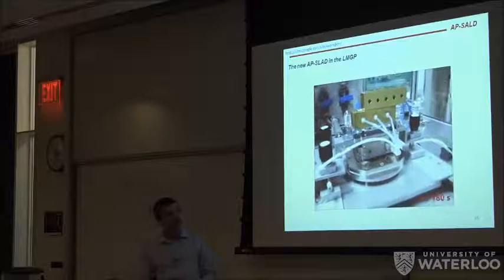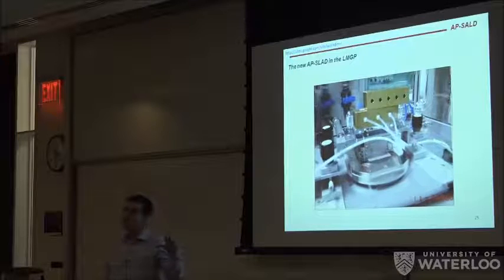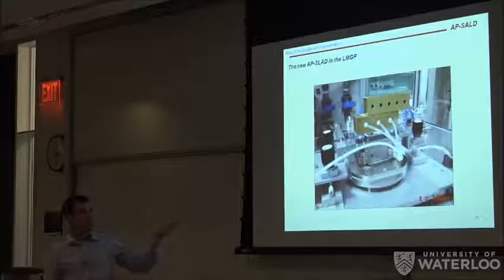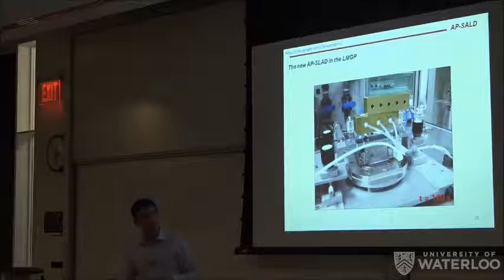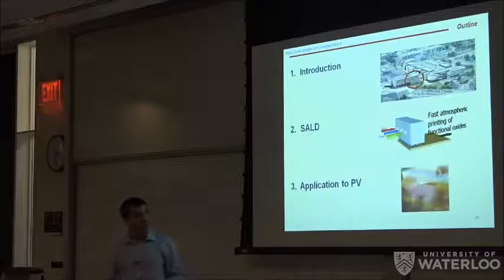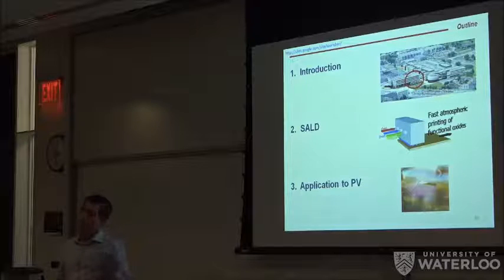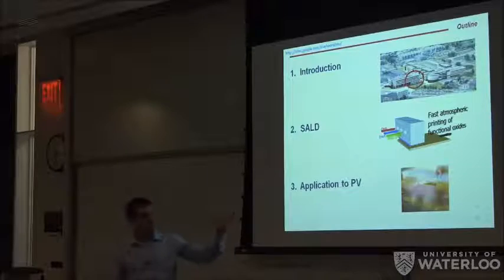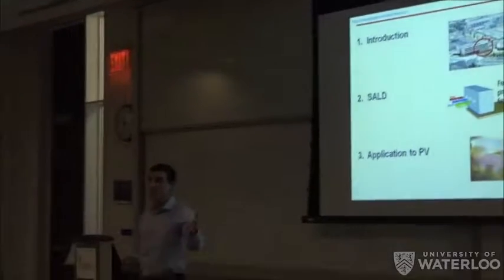So it's really convenient. Once the sample is adjusted, everything is adjusted, saturated, you can see that you can grow a lot of samples in a short time. So it's very convenient, and it's one of the main advantages. Then you have many other advantages, such as the possibility of printing oxides in ALD mode, CVD mode, but it's a large scale, fast deposition technique, so it's very, very convenient.